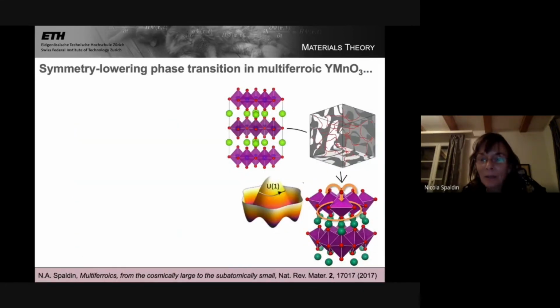In multiferroic yttrium manganite, these defects are not two-dimensional like in the case of the ice. They're one-dimensional defects because of the special symmetry associated with the phase transition, going from the structure at high temperature where there are no dipoles to the structure at low temperature where dipoles form. And mathematically, the form of the potential that takes us from this high symmetry to this low symmetry structure is this kind of Mexican hat-like